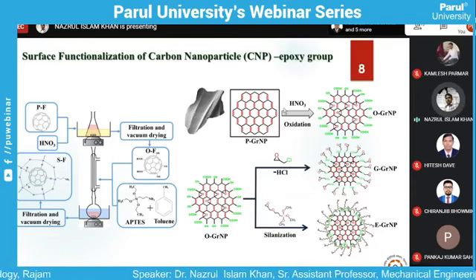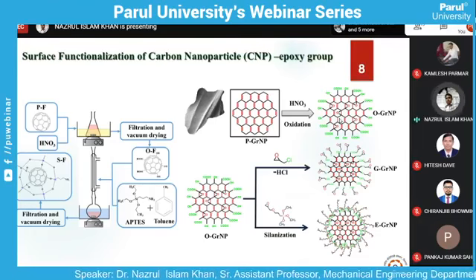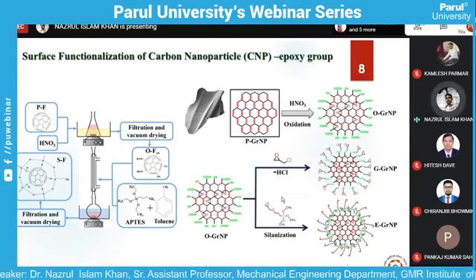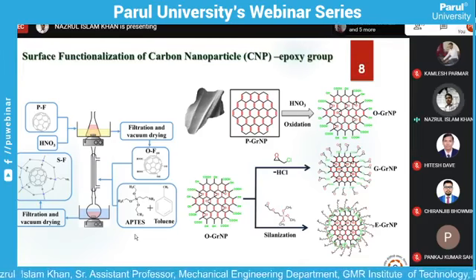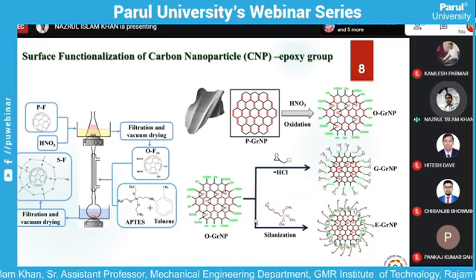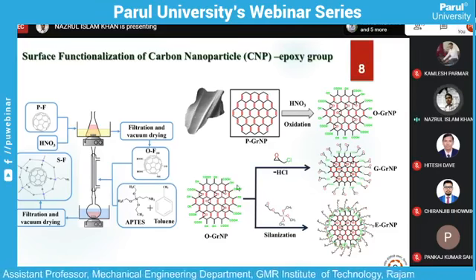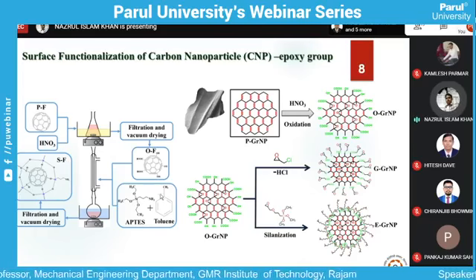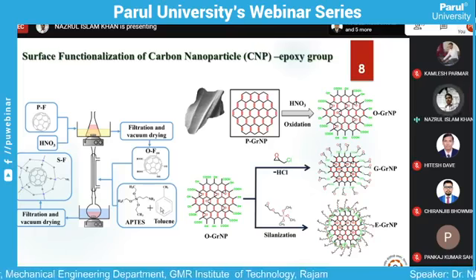For that, we did oxidation so that we can introduce some oxygenated functional groups like OH group, ketone group, or carboxylic group on the surface. This carboxylic group, when we add with the silane group, we have used APTES, aminopropyl triethoxysilane, or GPTMS, glycidoxy propyl trimethoxysilane. These are surface functionalization groups having end groups of SiO and NH2, or in GPTMS, epoxy group and SiO.